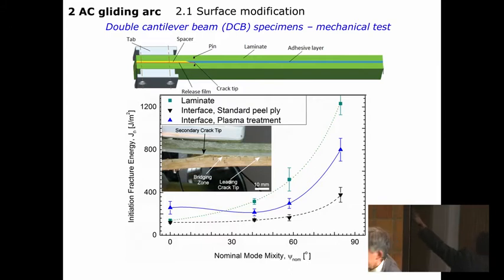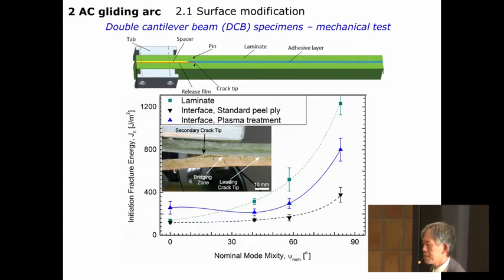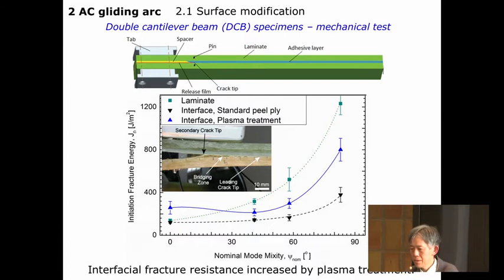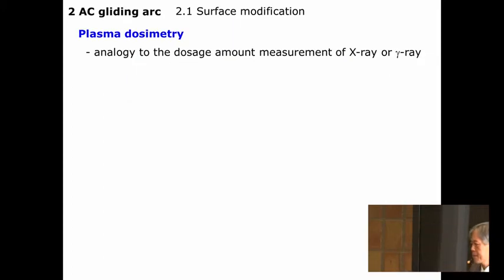But then I probably have to focus on two different things. Black is with the normal mechanical roughing called peel ply, and blue is by plasma. And I'm happy to see that in all cases, plasma treatment consistently shows higher fracture resistance. So, okay, then I have to talk just a little differently from adhesion stuff, because I've seen something quite interesting and unexpected.